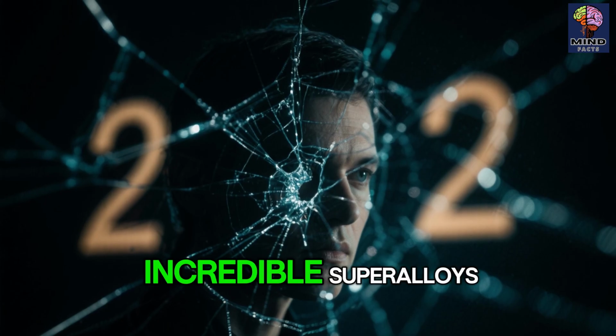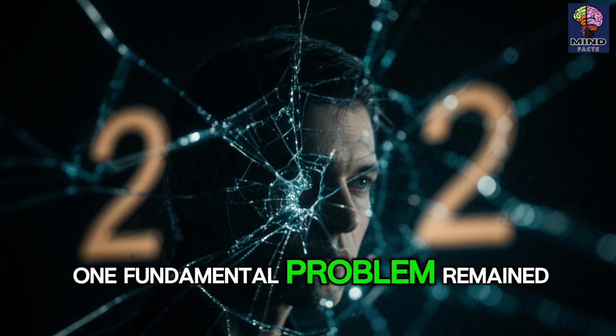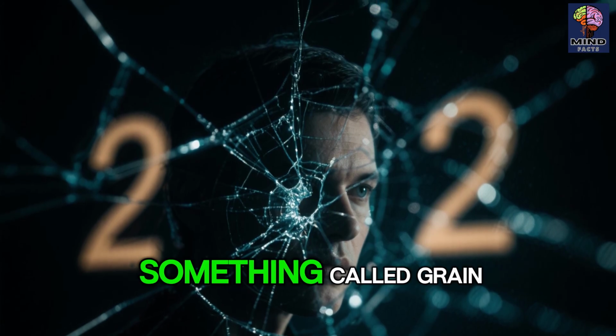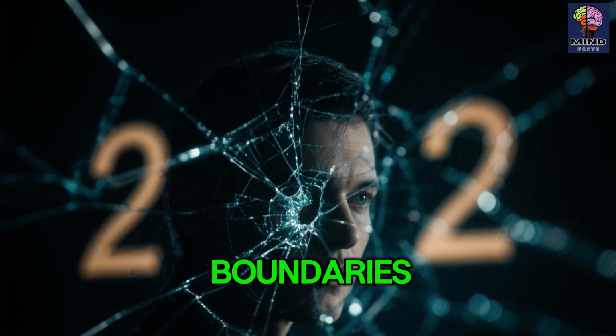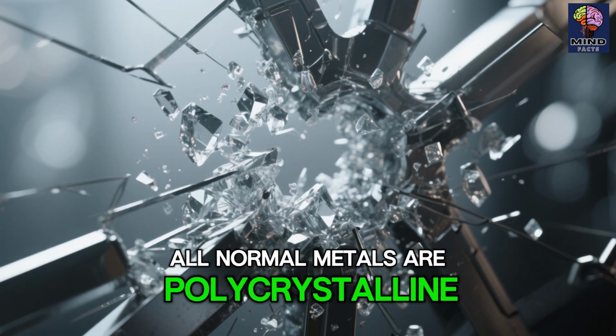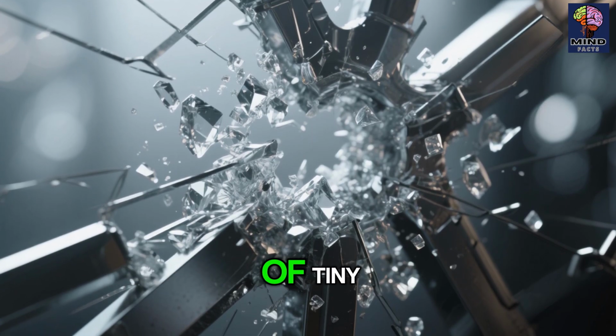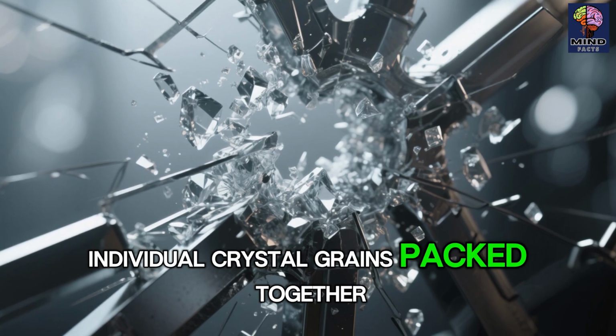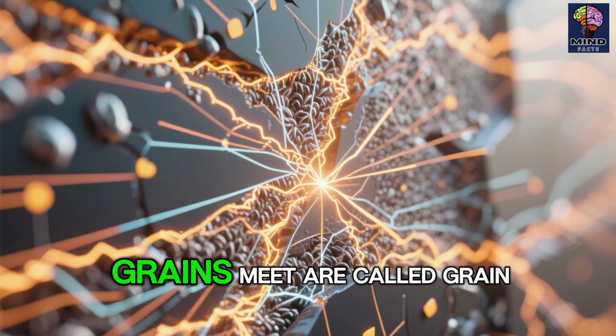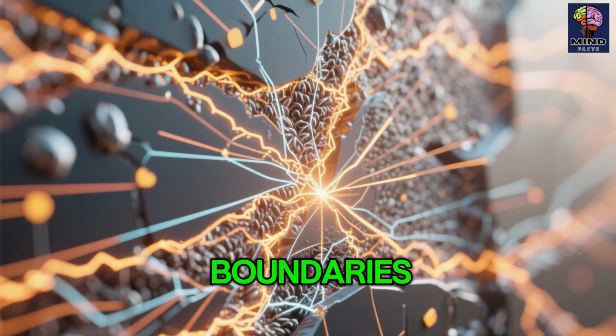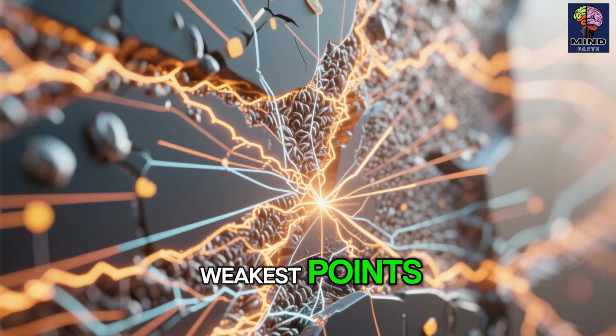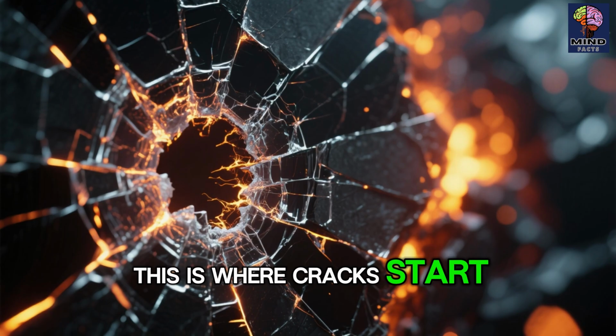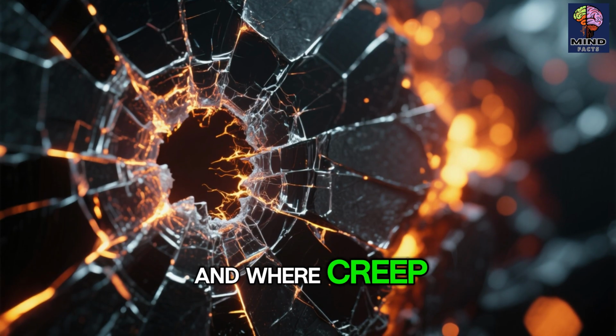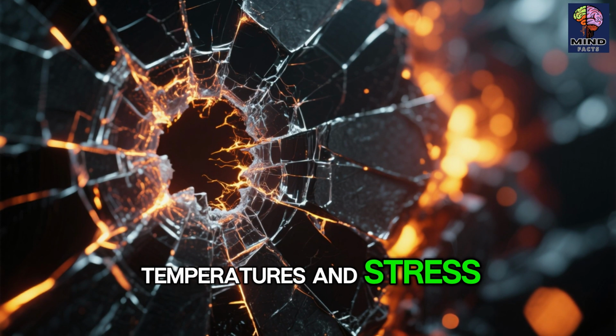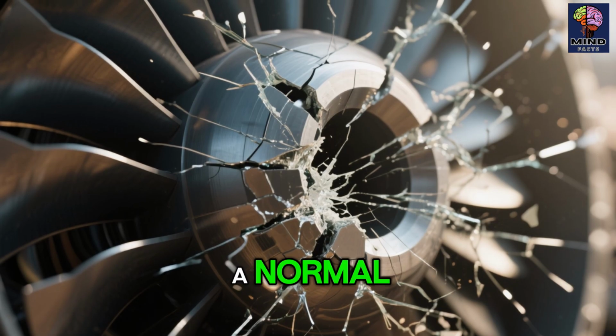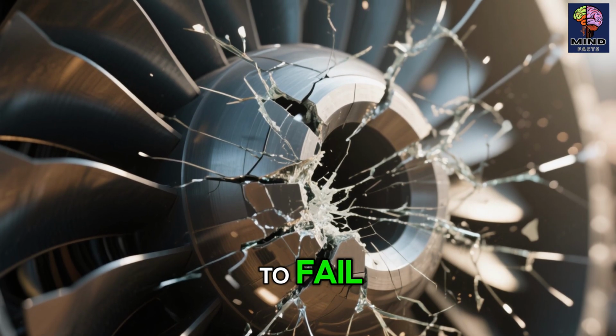But even with these incredible superalloys, one fundamental problem remained. The enemy was something called grain boundaries. All normal metals are polycrystalline, meaning they're made of millions of tiny individual crystal grains packed together. The borders where these grains meet are called grain boundaries, and they are the material's weakest points. This is where cracks start, where atoms diffuse away, and where creep accelerates under high temperatures and stress. A turbine blade made of a normal grainy metal was still doomed to fail.